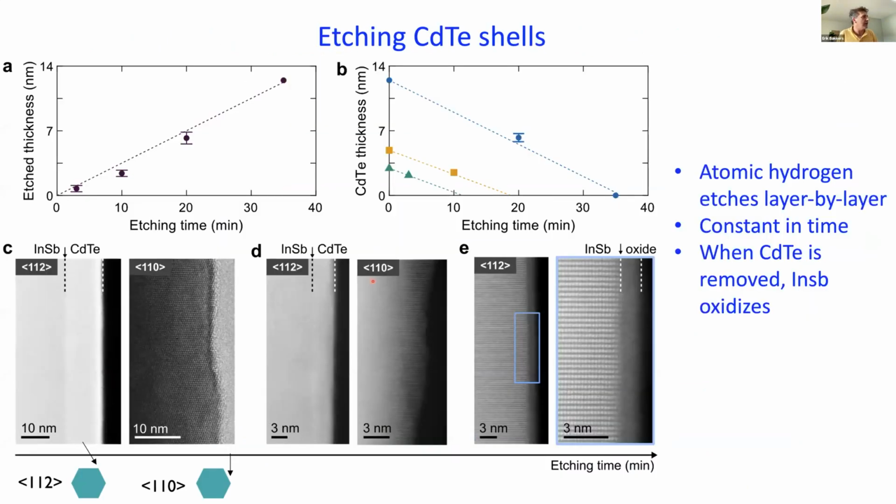Yeah, so we developed a trick here, and that is that we first grow a very thick shell of cadmium telluride, and then we etch it back by using atomic hydrogen. We found that this etching is actually a very nice mechanism. It seems to etch away the cadmium telluride layer by layer, and it results in very flat layers of